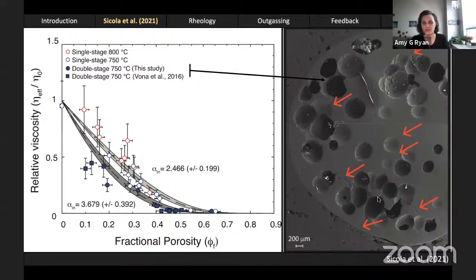And what she observed was a series of very, very fine microcracks extending between the bubbles and out to the surface of the core. The microcracks are shown here with red arrows. Her interpretation is that they form during the quenching process when crossing the glass transition. Ultimately, the formation of these microcracks allows the pore fluid that was held in that bubble to leak out of the system without us even really detecting it. So her interpretation overall is that the difference between the single stage and double stage materials is because they're inherently different.